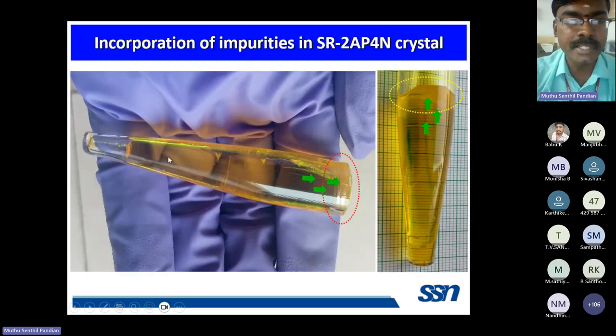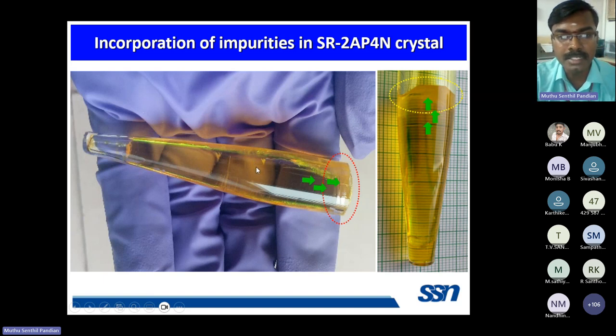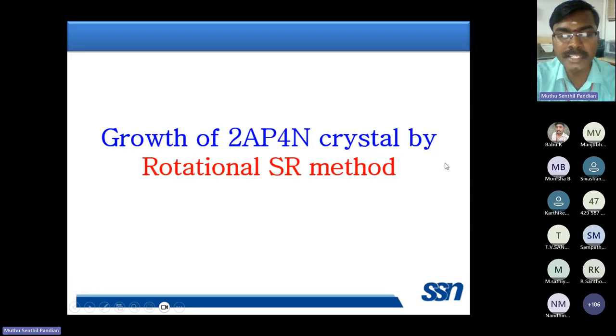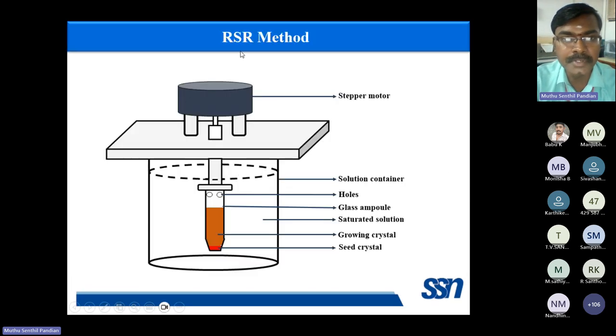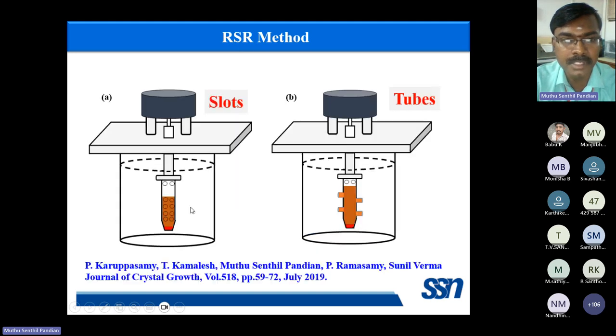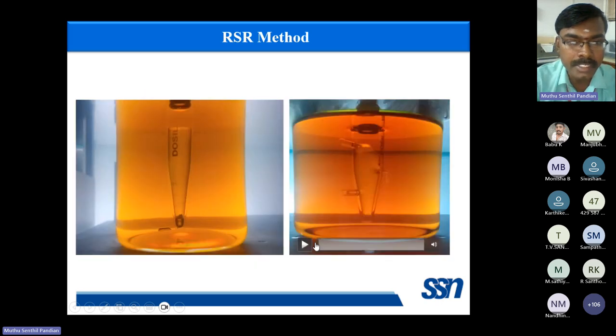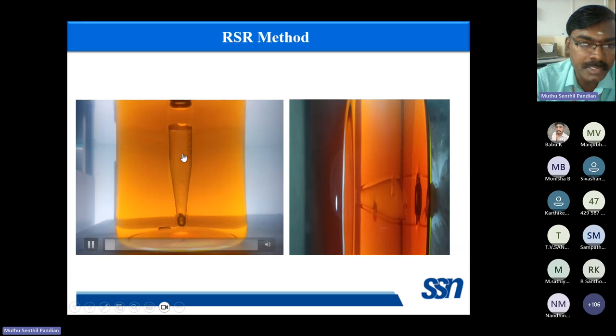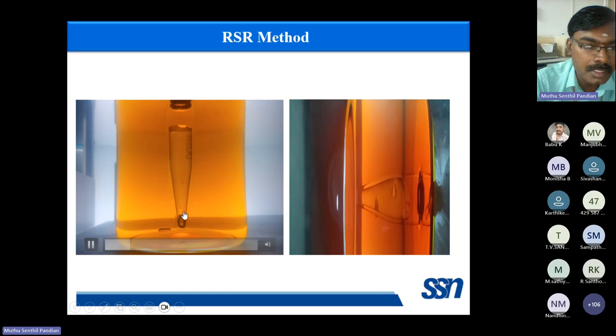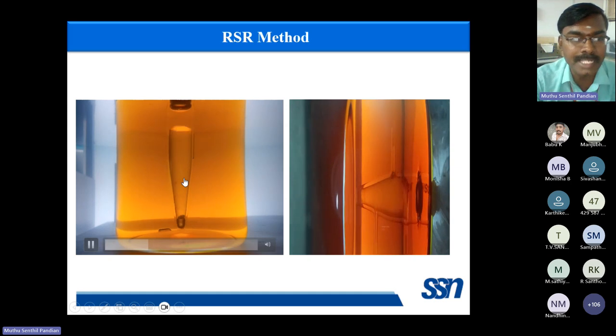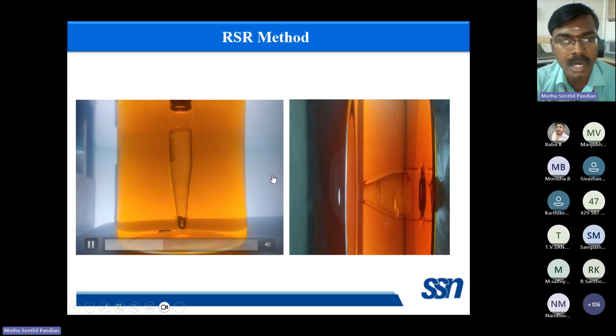So when we grow the crystal by this conventional SR method, there is no chance for the impurities to go out of the SR method glass ampoule. In order to avoid the impurity segregation in the SR method, we have introduced this RSR method, the rotational Sankaranarayanan-Ramasamy method, with the slot and with the tube. So here what we have done is we completely rotate the entire setup of this RSR method with the slot and with the tube. We mount the seed crystal at the bottom of the glass sample. We rotate the complete setup of this RSR method so that the impurities are pushed up from inside the glass sample to outside the glass sample. One can easily minimize the impurity segregation in the RSR method grown crystal.